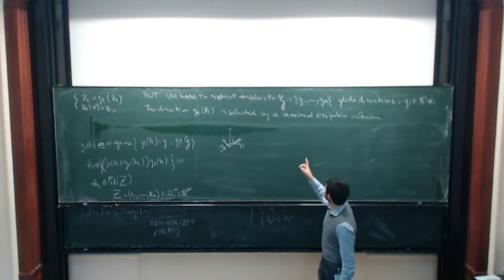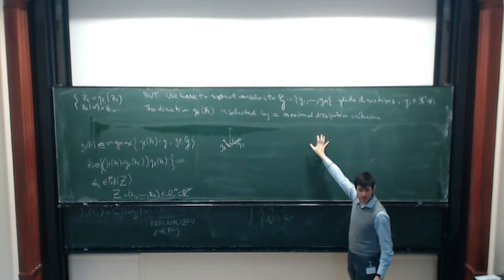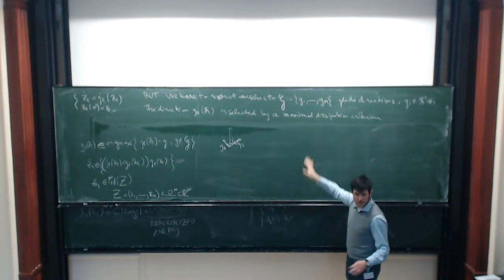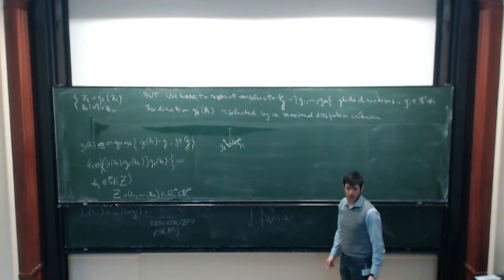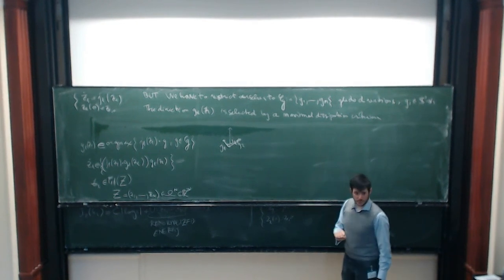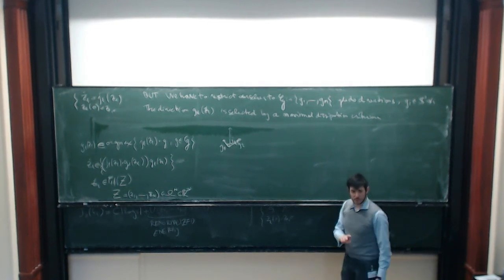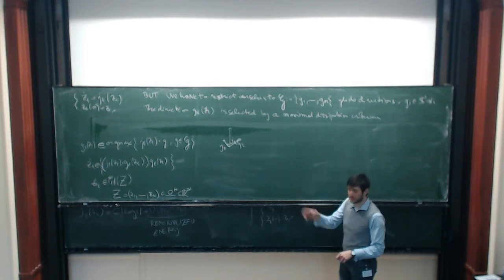The glide directions are given by the crystal structure of the material, encoding glide planes and admissible motion directions. The glide direction a dislocation follows can change over time: at some point it may be more energetically favorable to switch directions, dissipating more energy along a different one. These direction switches are precisely the cross-slip and fine cross-slip behaviors described by Cermelli and Gurtin, observed in experiments and numerical simulations.